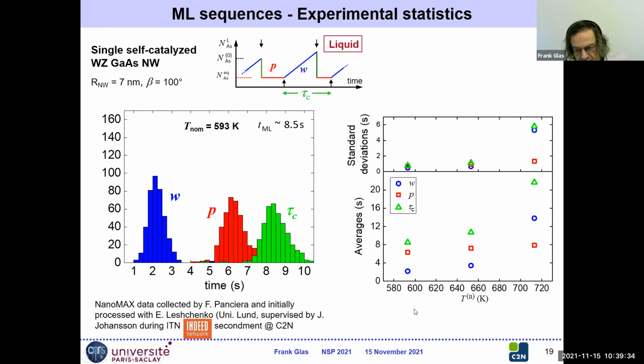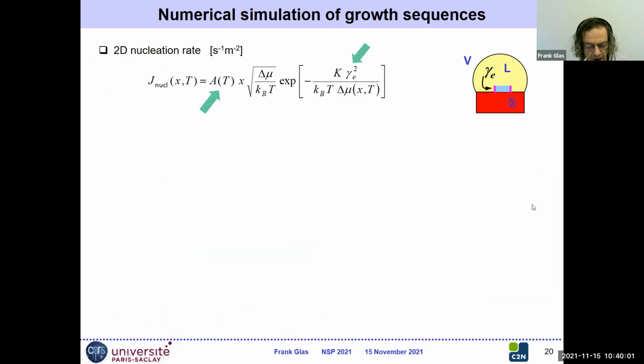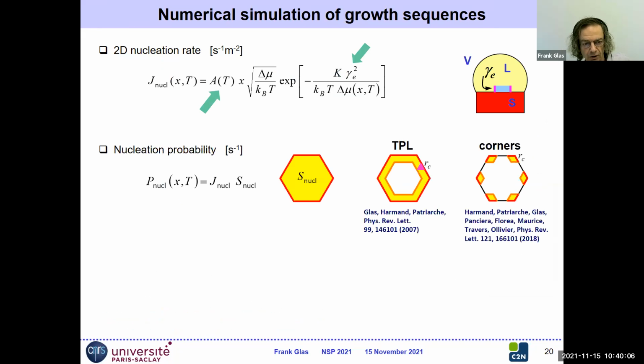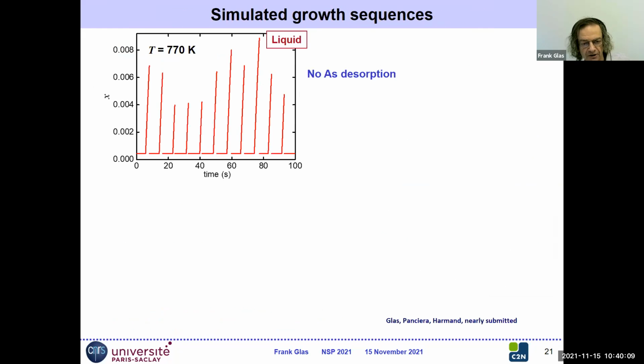And basically what you see is that the average increases if the growth temperature increases, which is nothing else than, in first approximation, due to the desorption of the group 5. So temperature increases, there is more desorption, so it takes longer to grow monolayers. However, some times increase much faster than others. In particular, the propagation time increases very slowly, whereas the waiting time increases much more sharply. So this can be, I'm not going to go into the detail, modeled numerically and analytically.